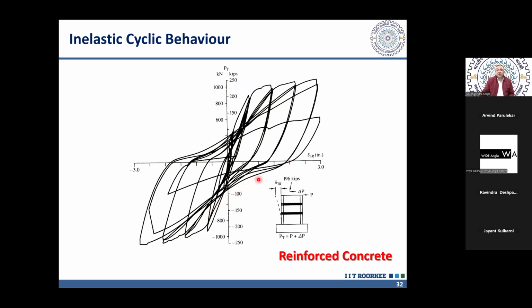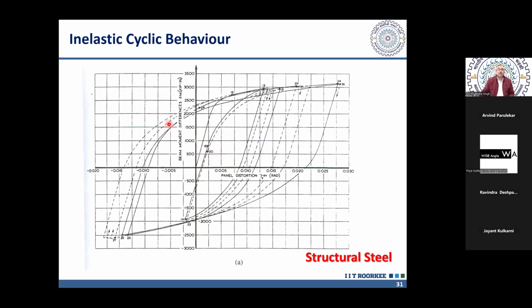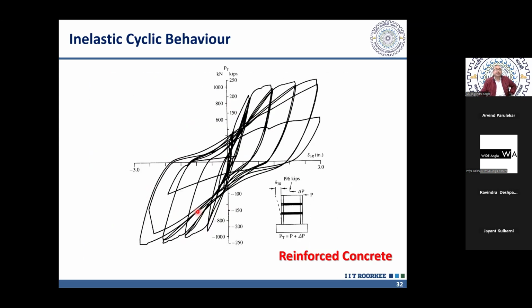And then the shape of the curve, if you see here, this load displacement curve here, the area is reducing. This is called pinching. So due to pinching, if you compare it with this curve here, you can see that the area here is much larger. And the energy dissipated by this structure per cycle is equal to the area of that cycle. So if I take the hysteretic curve in one cycle, area under that cycle, or area of the hysteretic loop in that cycle, is representing the energy dissipated in that cycle. So we can see in case of RCC structures, due to this pinching, the area of the hysteretic loop is reducing and the energy dissipated per cycle is reducing. So under the same displacement, it will be able to dissipate less energy.